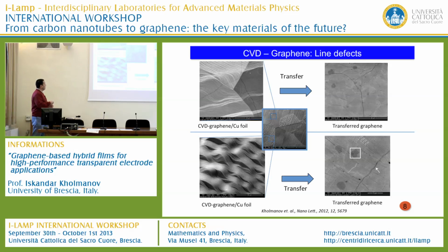If you see that the different grains of copper have different roughness, and graphene during the CVD growth process conforms to the surface roughness of the copper foil. So when you transfer this kind of graphene from this kind of copper substrate, you may obtain graphene on a silicon or on a glass substrate. You may obtain very different other line defects.